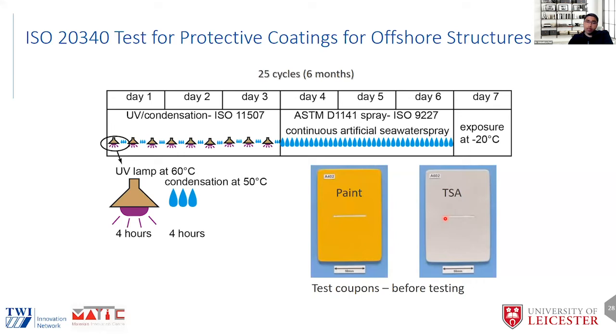We created a scribe. This scribe is about 50 millimeters in length with a width of about 2 millimeters, and this went all the way through to the substrate. So the steel is exposed in both cases. We subjected these samples to 25 cycles of 7-day cycle each, with a 3-day UV condensation at 60 and 50 degrees for 4 hours each, followed by 3 days in an ISO 9227 type system.